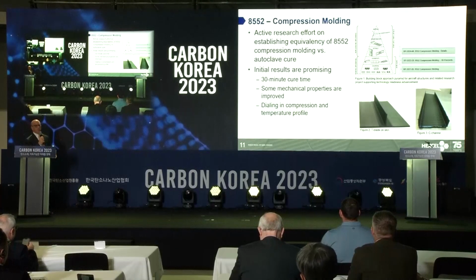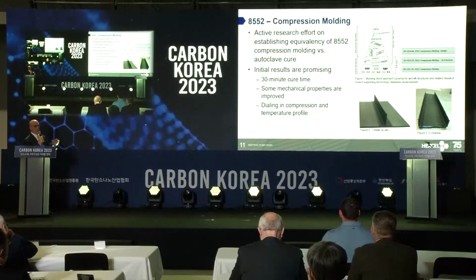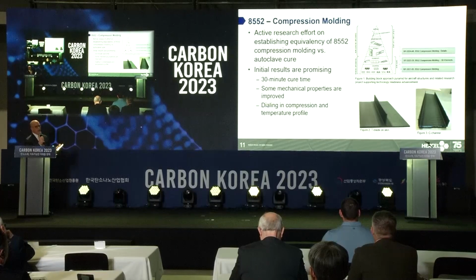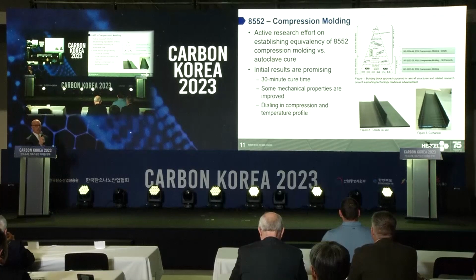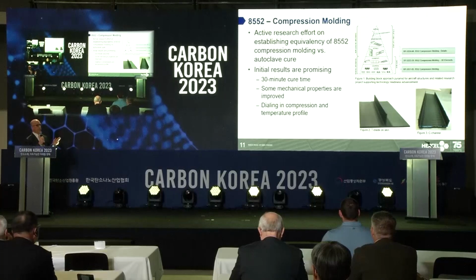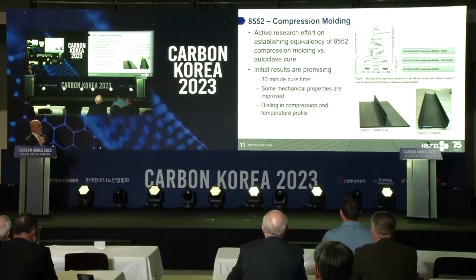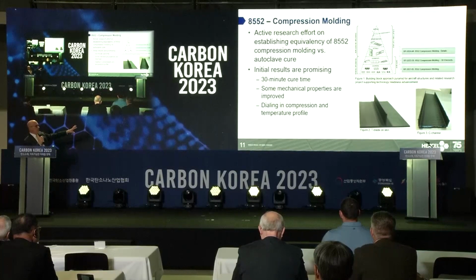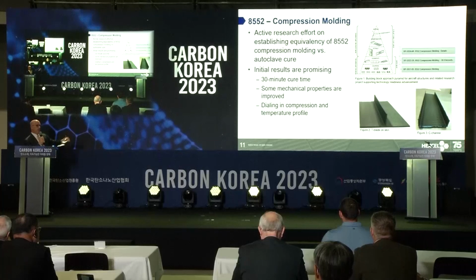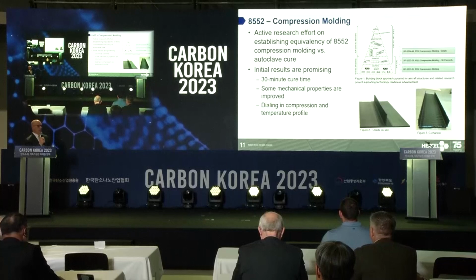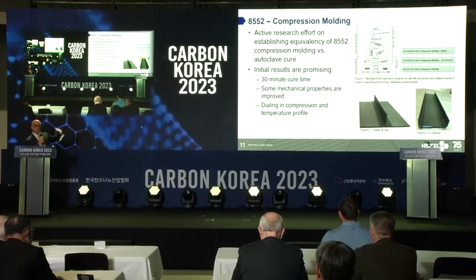So we started this project about a year ago and have a lot of data completed. And actually, with a 30-minute compression molding cure cycle, we're getting equivalent properties. In a couple of cases, properties are actually slightly improved over the autoclave cure system. We're completing some of the testing on this, but one of the ideas that we have is to do an equivalency qualification of this system, and this gets you from a 6-hour cure time to 30 minutes.